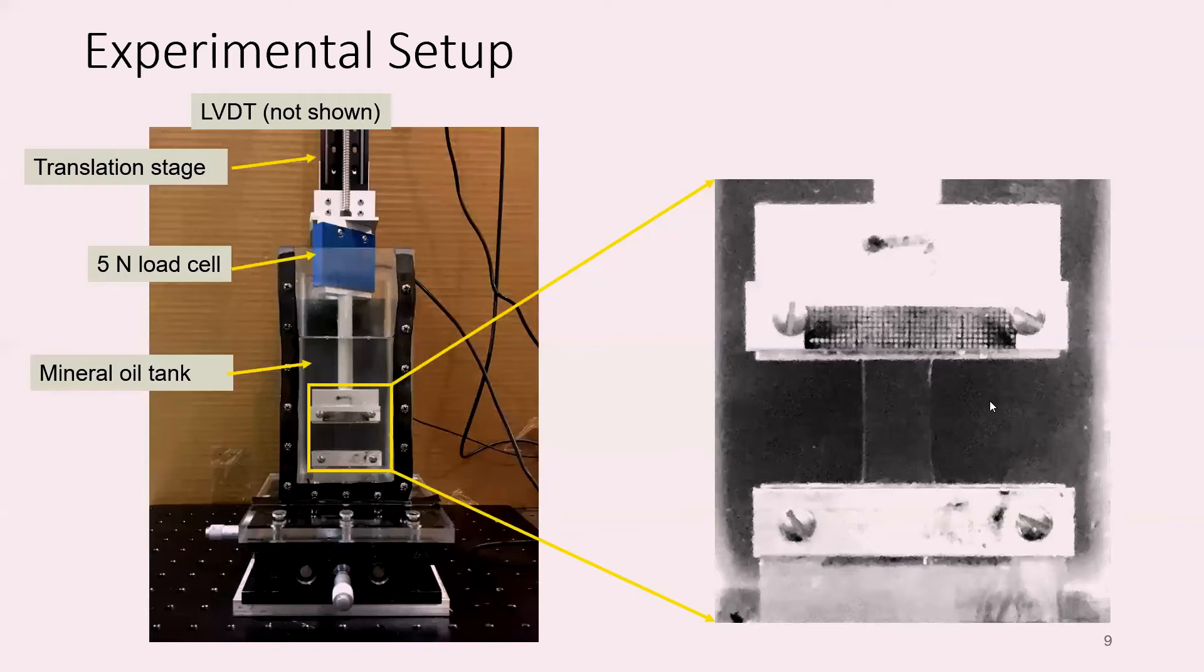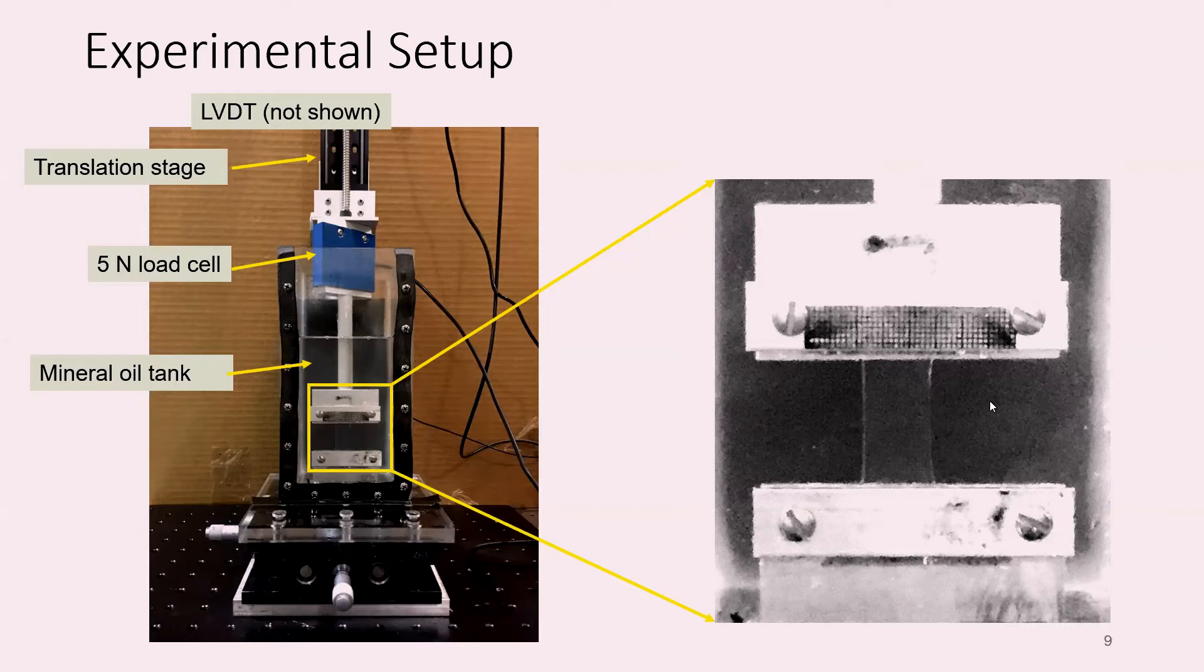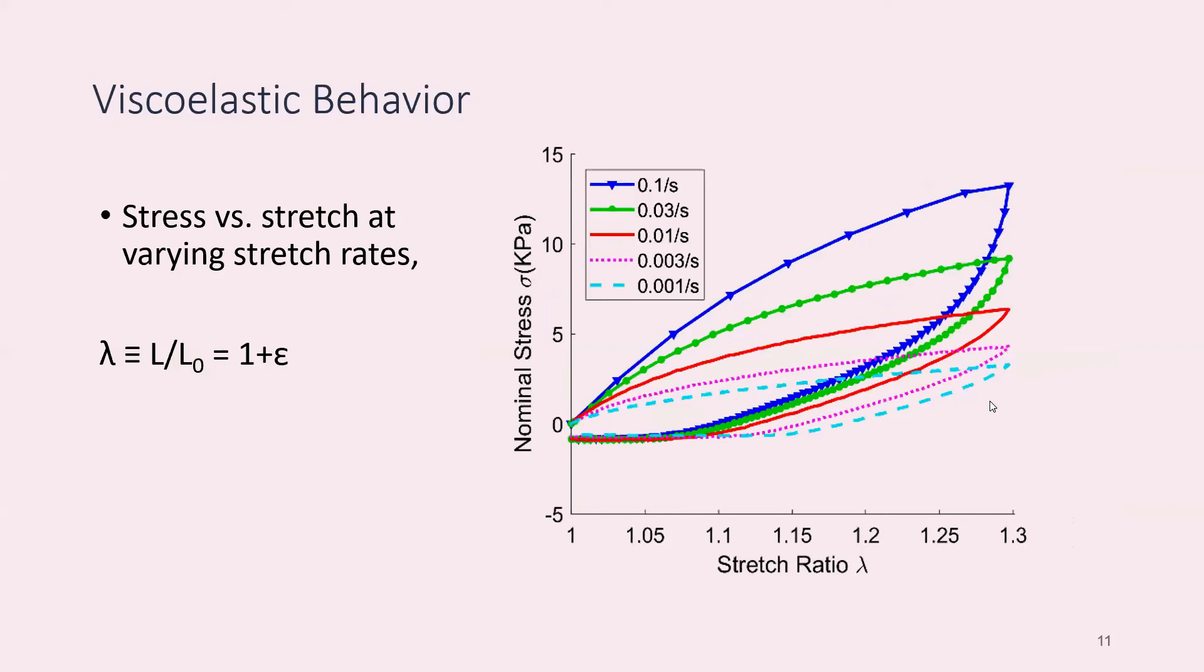This gel is based on polyvinyl alcohol as the polymer. The green and red dots are cartooned to denote permanent cross-links, or chemical cross-links, basically covalent bonds between the chains, and transient cross-links, or physical cross-links, effectively ionic cross-links between the chains. This gel is mostly water, very stretchable, very viscoelastic. The idea is that the transient bonds can break and reform, lending a certain viscoelasticity to the material.